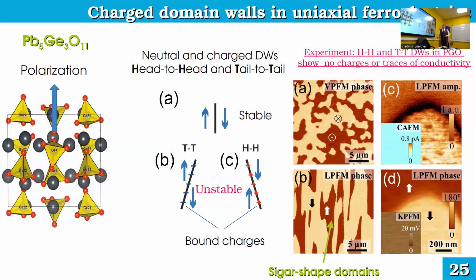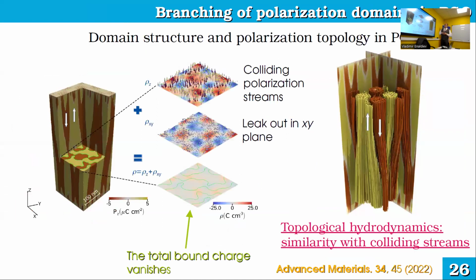Very interesting case of lead germanate. People studied this thing, and they found no signs of conductivity. Here you can see conductive AFM near the head-to-head domain wall, and no signs of charges. It's measured with Kelvin probe force microscopy, again near the same domain wall. It's pretty curious behavior actually, and we employed some modeling to explain this. So we modeled a big chunk of this material.